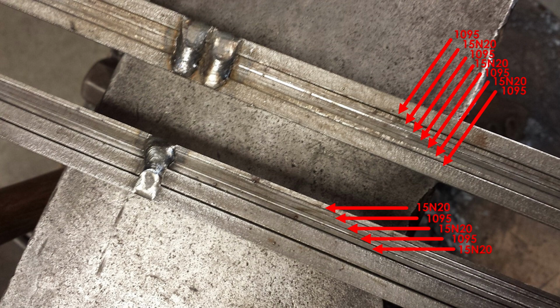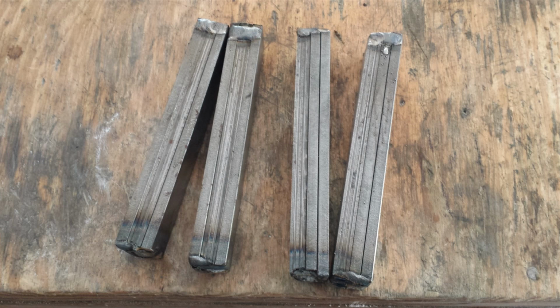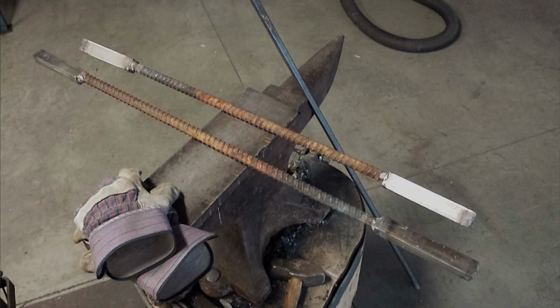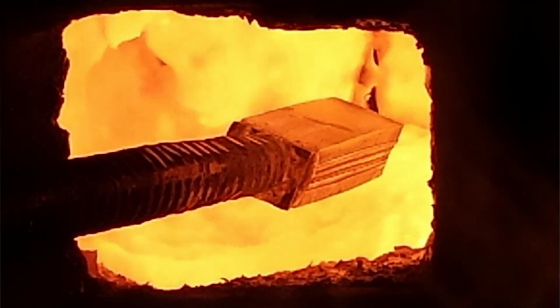The billet is about 12 inches long and 1 inch wide by 1 inch thick. I split the two billets in half to make 4 billets 6 inches in length each, which were easier to handle in my forge. Each one of those weighed about 650 grams. I then welded a piece of rebar to each billet to get ready for forge welding. This was the chevron billet getting ready to weld. I was using a propane forge made of refractory material that I designed myself. The forge will get hot enough that the bottom floor became molten during operation.